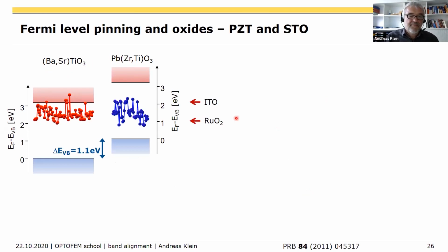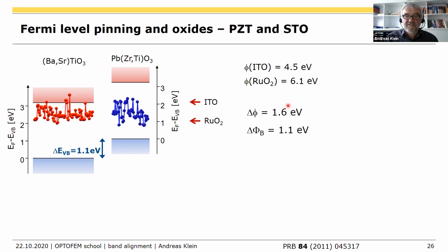If we make the Schottky barriers for ruthenium oxide, the Fermi level with ruthenium oxide is somewhere here, and the Fermi level with ITO is somewhere here. So with ITO, we get the Fermi level which is close to the upper limit of the variation of Fermi energies, and with ruthenium oxide, we have a lower Fermi level. And the variation is in principle the same for both materials. If you go for PZT, the work function of ITO is 4.5 eV, the work function of ruthenium oxide you measure by XPS is 6.1 or even 6.5 eV. So that means the difference in work function is 1.6, and the difference in the Schottky barrier height is about 1.1 eV. So we would expect a little bit of pinning.